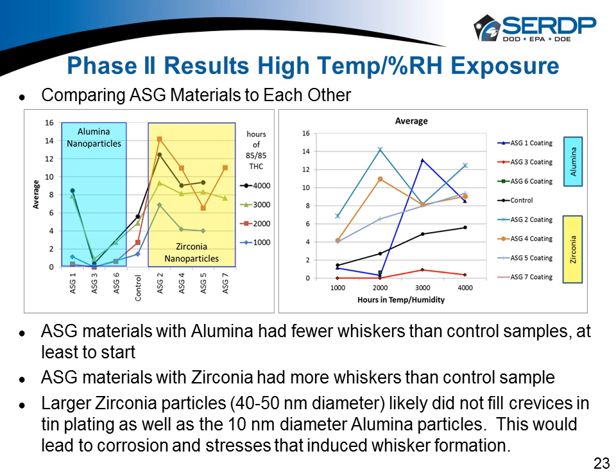I'm going to go back to slide 23, and I had Dr. Ross Wilcoxon. Ross did all the graphs on this, and I had him pull this one. The right side will tell you things, but I think the left side of the graph is much, much more telling. You can see in the yellow, those are the results for the samples that we're dealing with liquid glass coatings that contain zirconia particles versus the light blue here. That's the liquid glass that contained alumina. And you can see it's heads and tails difference, except for one coating here that didn't play very well. Zirconia just doesn't give the same benefits that alumina does. In the middle between these two blocks is our controls. And so you can see zirconia performed much worse than our controls, and the alumina did much, much better.